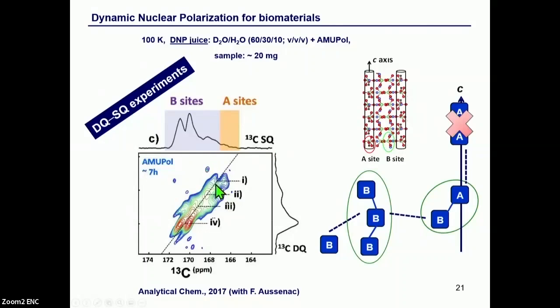And it's very difficult to know how the carbonates are located in the structure. Without going into the details, if you look very carefully at this double quantum, single quantum carbon-carbon experiment, it was possible to exclude definitely the association of A sites, and the most favorable association was a clustering of B sites, and we were even able to detect A-B association by looking at this kind of experiment.